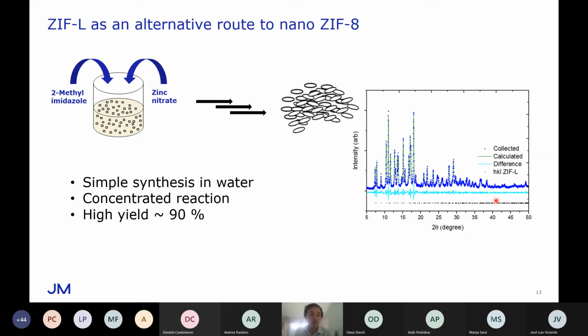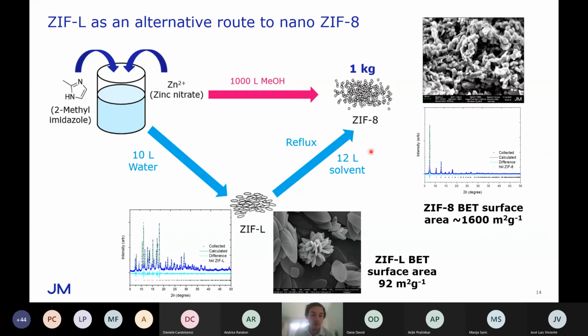What we can then do is convert that ZIF-L into ZIF-8. The way we convert ZIF-L into ZIF-8 is by refluxing it in a solvent. We can change the structure and the particle size into the ZIF-8 structure and nanoparticle size. Now, this reaction is known in literature. However, we've managed to optimize the conditions to produce ZIF-8 with the right particle size, right phase purity and the right surface area. If we compare our new route via the ZIF-L to our original route directly using methanol, we can see there's a vast reduction in the amount of solvent that we are using, which makes this reaction much more scalable and more applicable to commercialization.